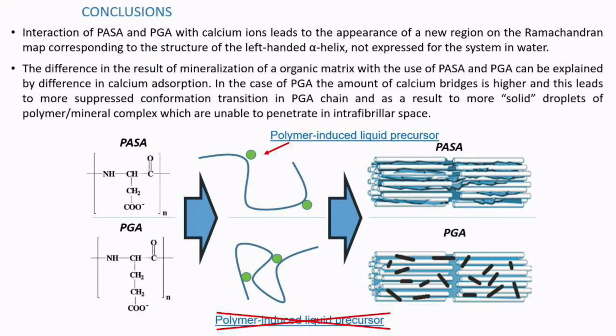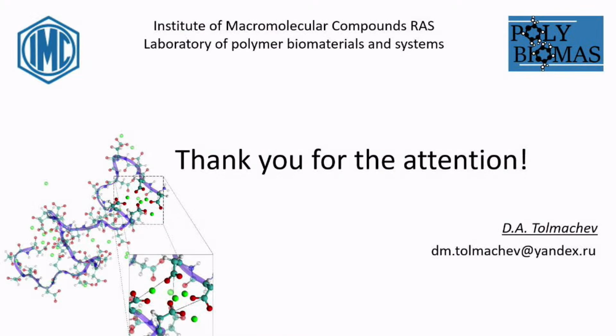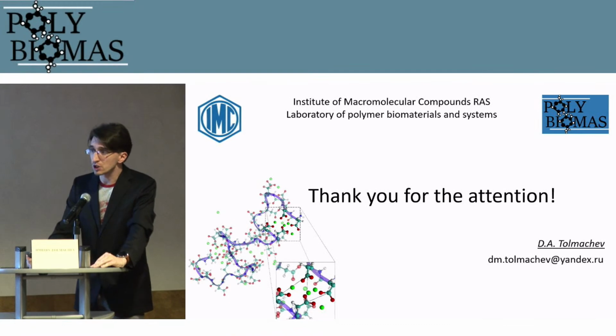So it is important to know that we performed some additional simulations with different salts. It's mainly calcium phosphate salts, and we obtained similar results, which show that in the case of aspartic acid, the organomineral complex is more flexible than in the case of glutamic acid. So this is all for now, and I'm ready to answer your questions. Thank you very much.